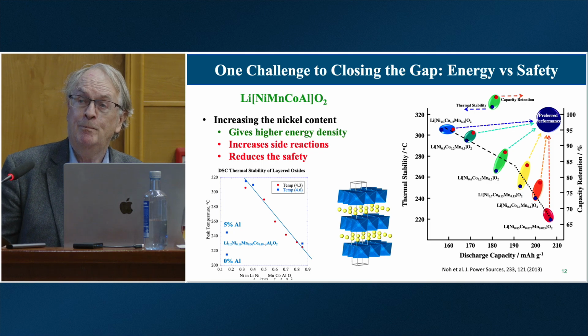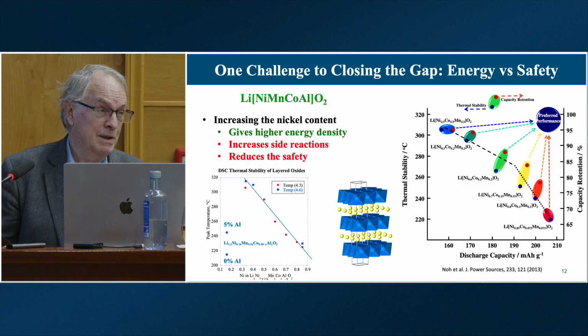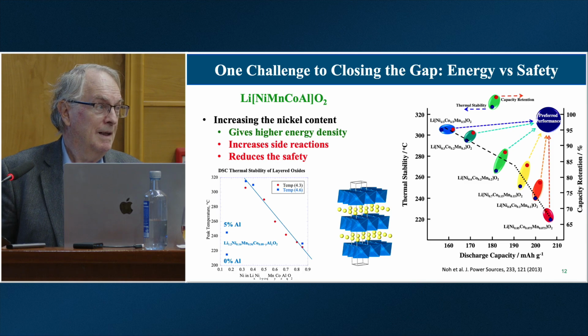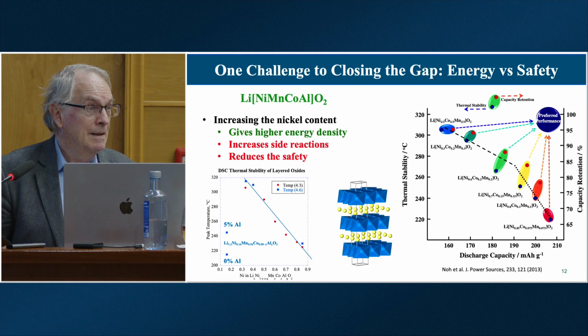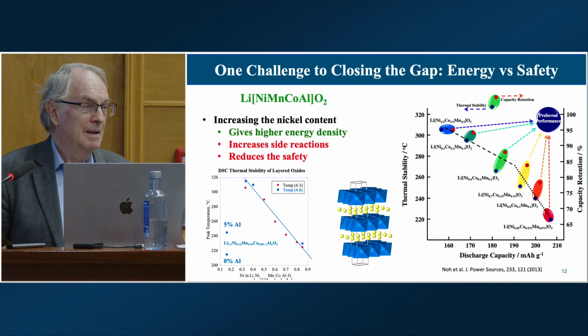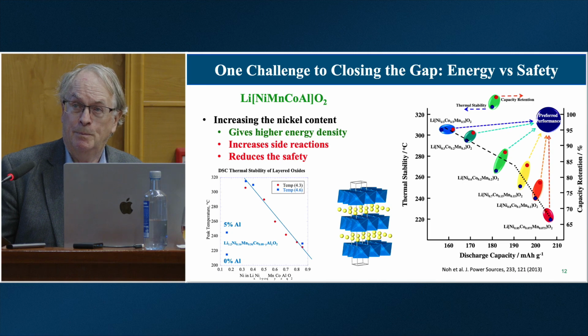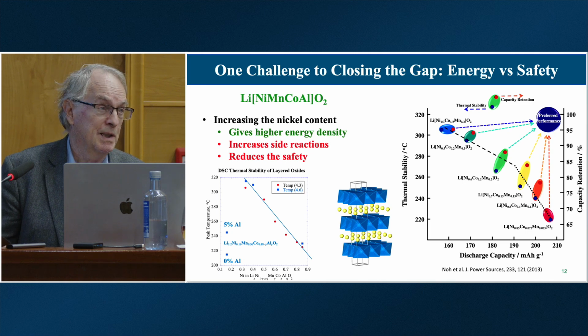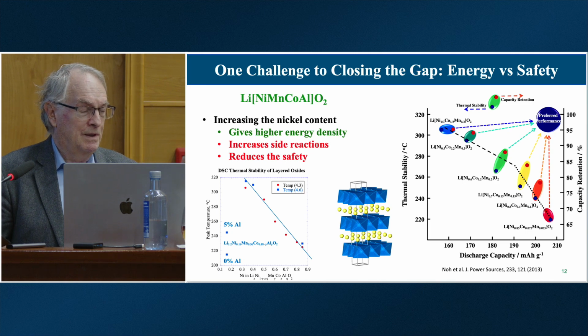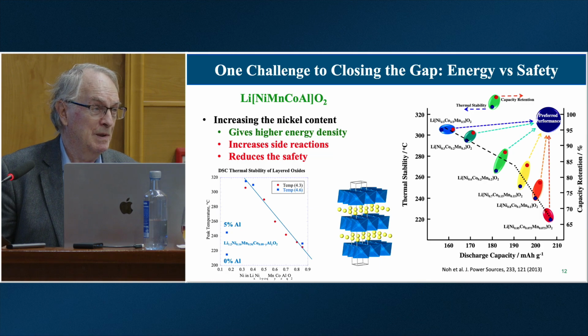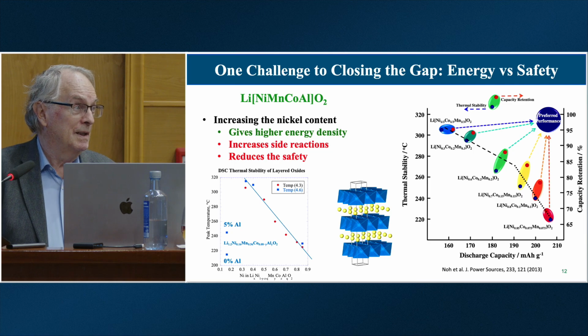So our goal is to increase the stability of these materials, get the energy density as high as we can, and get the capacity retention as long as we can. And the bottom right-hand plot is exactly the same plot for different charging voltages, different compositions, but the common thing in there, it all depends on the nickel content.